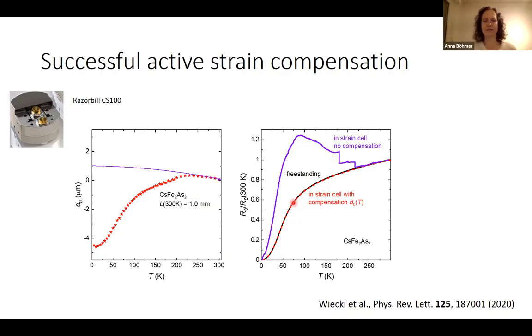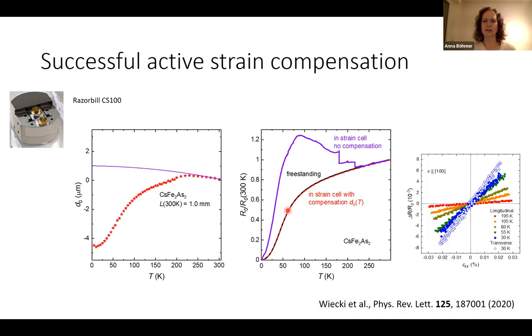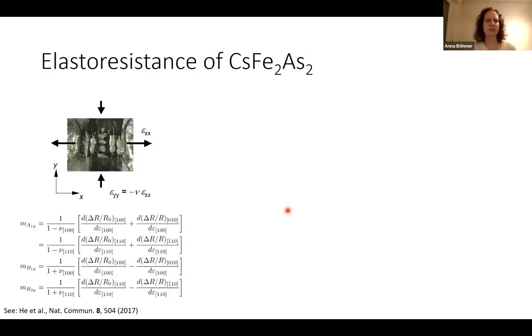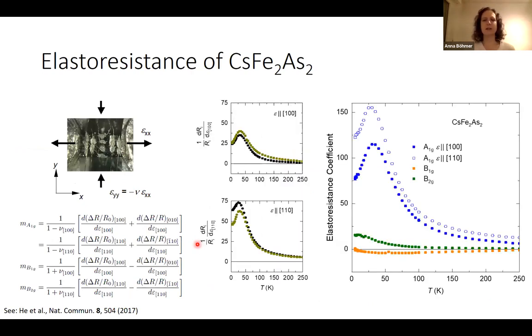So once we have a sample, say at low temperature in this state, we can then apply small strain sweeps and measure the elastoresistance. That's what we did again. And here we use an 8-contact configuration to get longitudinal and transverse resistance at the same time, inspired by this work here. And again, the same symmetry decomposition for the coefficients. And here's already a result for the cesium sample. So the longitudinal and transverse elastoresistance for a sample in 100 direction and in 110 direction.